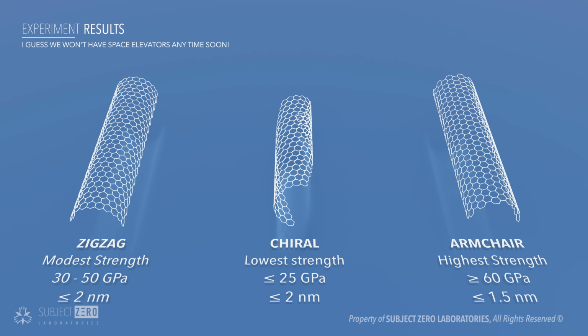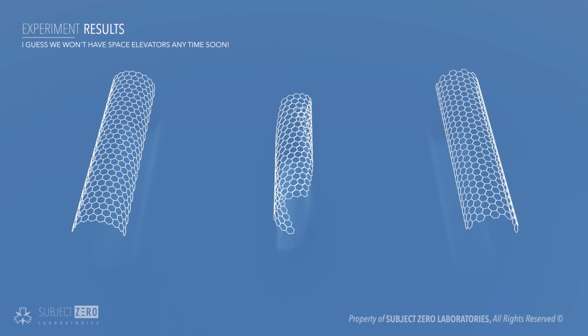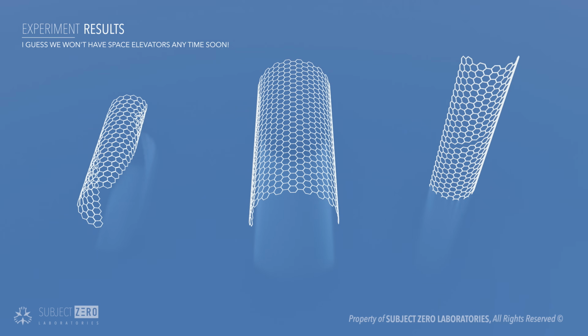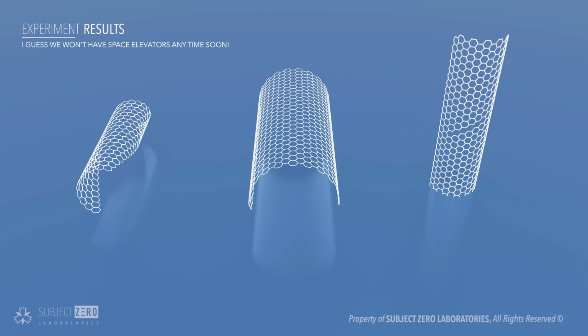The weakest tubes were in the diameter range of 1.5 to 2 nanometers plus, while the armchair configuration yielded the highest strength of more than or equal to 60 GPa, and chiral showed the lowest strength, less than 25 GPa. Now keep in mind that these tubes were not perfect, hence why we won't see the strength near 100 GPa until they manage to make defect-free tubes. The ultimate conclusion is that the strength of nanotubes is a linear relationship between the chiral angle, diameter of the tube, and size of the defect.